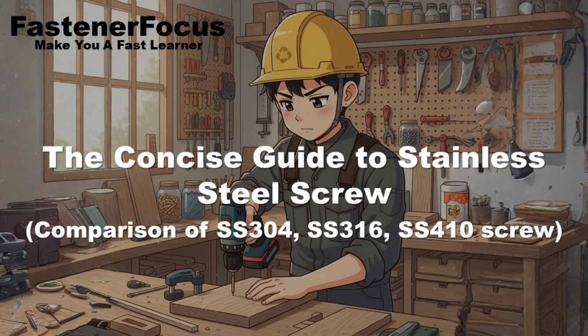First, it is about deep cleaning. During the manufacturing of the screw, the cutting, the threading, the cold-forming, microscopic particles of free iron from the tooling or handling equipment can become physically embedded in the stainless steel surface. These iron particles are not stainless steel, and they will immediately rust upon exposure to moisture, initiating corrosion right on the surface of your expensive stainless fastener.